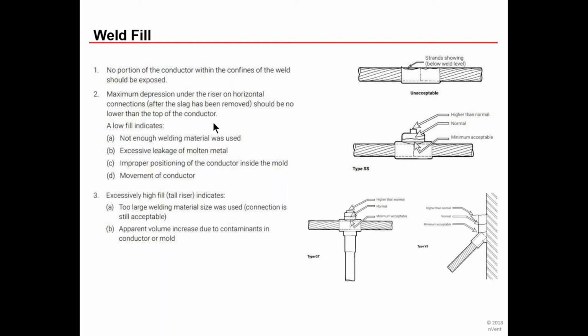Maximum depression under the riser on horizontal connections, after the slag has been removed, should be no lower than the top of the conductor. You cannot assume slag is part of the weld. That stuff is so brittle you could knock it right off. And here are some indications of a low fill, and then why you may have had a high fill. Low fill, you may not have used the correct material, your weld material may have deteriorated to the point that you're leaking material when it goes to form, or something happened to your conductor. And excessive fill, you can see here, means you have too many contaminants, or the weld material was the wrong size for the connection you were doing.